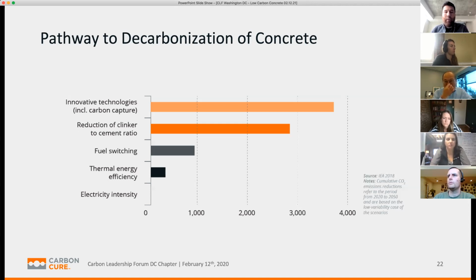And those two things, I'll start with the one that's the darker orange, which is labeled as reduction of clinker to cement ratio. What that means is, again, that replacement of cement with other materials like fly ash or slag. So what that is saying is that if you really want to achieve a lot of decarbonization, you need to find a way just to use less cement. The trick there is that we don't actually have enough materials like that to have a global scale of replacement at the level needed. But a lot of research is underway in terms of finding different materials or additional material sources. And I think Teck will speak to some of this too, where you can actually replace cement with different materials and get high replacement percentages.